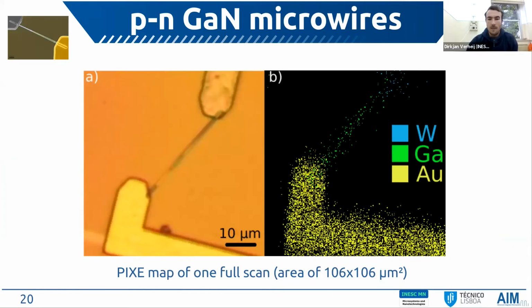So that's how far our measurements of the n-type microwires go. Moving on to the p-n junction gallium nitride microwires, I start by showing a proton-induced X-ray map of a specific area, which represents the emitted X-rays from the materials present in the irradiated area. Each material emits a specific X-ray with an energy which can be correlated to the material. We can see here the gold coming from the gold contact, the green gallium nitride signal coming from the microwire, and the blue dots coming from the tungsten in the titanium tungsten aluminum contacts.